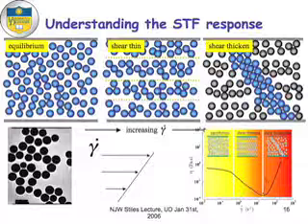And I've highlighted the particles here because this is a particular conformation where the clusters are spanning the cell of the device, and they're exerting very high stresses in the material. And so it's this transition from a fluid to these clusters and back, which is what we're looking at in this phenomenon, which is responsible for the energy absorption of this material, as well as the ability of the material to withstand very high stresses.